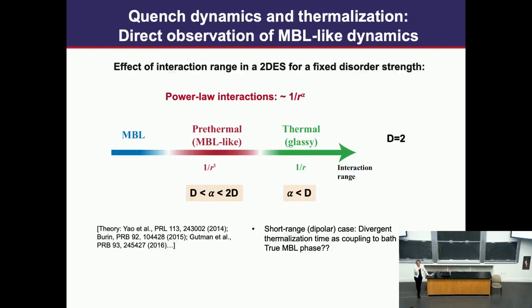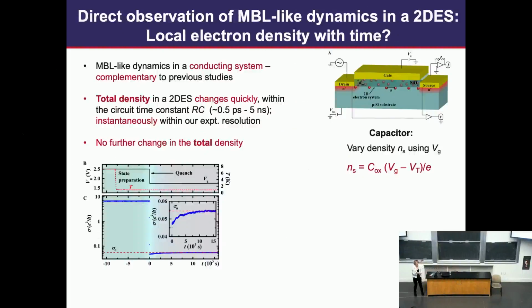We measured conductivity, but we cannot measure the density. You would expect that in case of MBL, it would take also a long time for the density to thermalize, remember those particles in a box. Now, since this is a capacitor, the total density changes instantaneously and cannot change anymore because we do not change the gate voltage. However, that does not necessarily imply that electrons are thermalized, because locally they're not thermalized, and there are local changes, and we expect that if this is the case, then this would have a big effect on the conductivity.